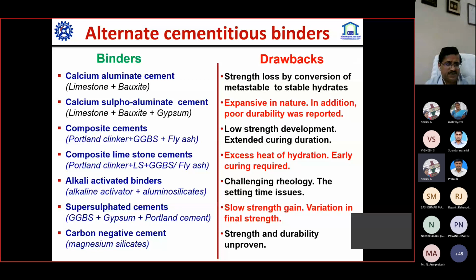Composite cement, as I have told, has only up to 30 to 35% Portland clinker. The balance 60 to 70% is GGBS, that is, ground granulated blast furnace slag, and fly ash. Definitely its initial strength is lesser, and it requires extended curing durations. Another is composite limestone cement, where we are utilizing limestone as a filler. Alkali activated binder is what I have called geopolymer binder. We worked at CBRI on two-component systems, but right now we are working on single component or single part, cement-like binders, and we are improving its rheology and setting time issues.